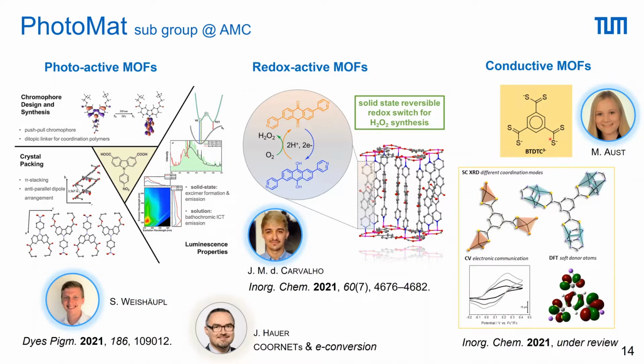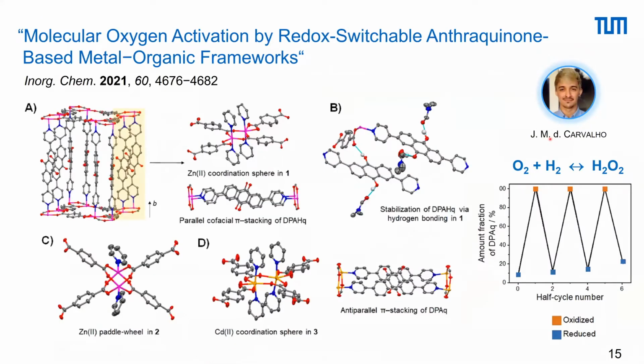Now let's have a look at Joao's redox active MOF system in more detail. So what you see here in all of these images is classic crystal chemistry, crystal engineering, and his thesis is heavily rooted in crystallography and crystal growing, basically. What he has been able to show is that by packing these anthraquinone linkers densely into the whole network, and the packing type depends on the metal you choose. It's very similar but distinctly different. So zinc and cadmium would make slightly different packing motifs, but in the zinc case, we were able to show that the reduced version of the quinone system, this would be the hydroquinone, can be stabilized by hydrogen bridging as a consequence of the packing density.